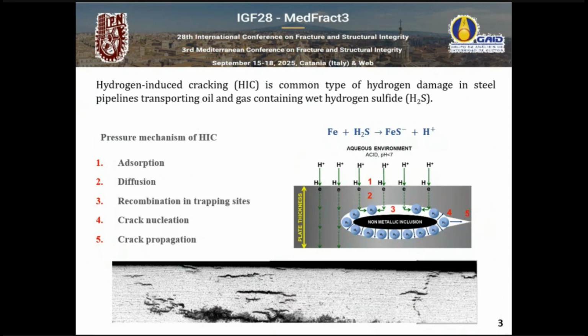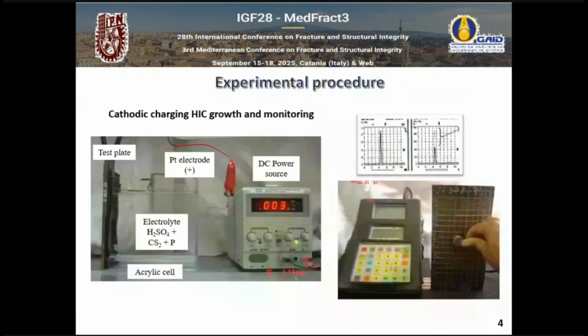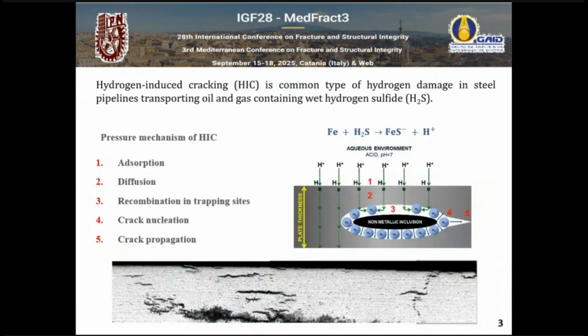And they just keep growing, and so at the end they make the plate look like a sandwich. Sometimes they can go stepwise because of the interconnection of cracks being nucleated at different depths in the plate. And sometimes, in the presence of high normal stresses, the cracks can deflect and form stress-oriented cracks, which are indeed very dangerous. Well, despite this knowledge that has been around for many years, there are several intriguing questions about this phenomenon.